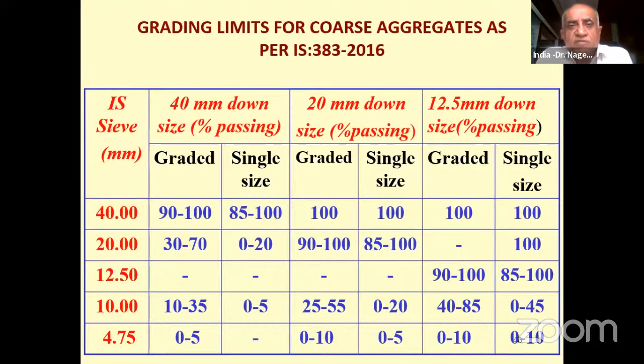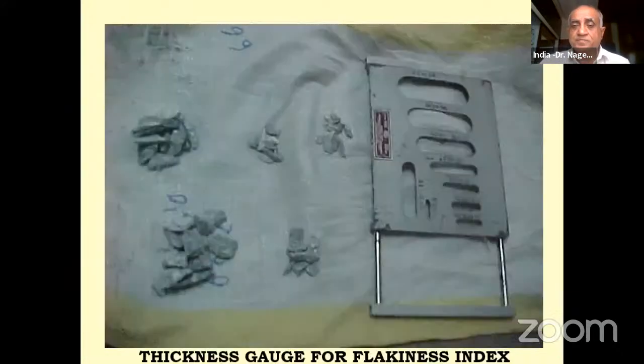Then again here, like fine aggregates, we have a table which tells you whether the aggregate is graded or single sized. For 40 mm, 20 mm and 12.5 mm, percentage passing requirements are given. So you can look into this, taking your test results, and these test results can be compared with the requirements in the table to see whether it is graded or single size. Normally 20 mm size aggregates conform to single size, whereas 12.5 mm size aggregates conform to graded size. So when you blend 20 and 12.5 in suitable proportions, suitable means what? Conforming to IS 383 requirements, then you can get really very good graded aggregates, total combined graded aggregates.